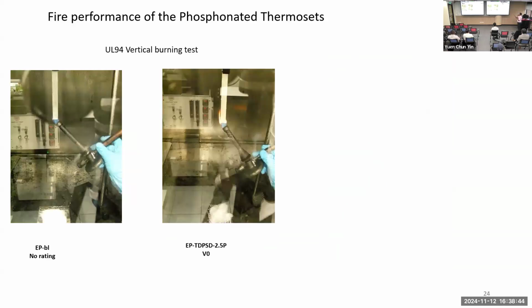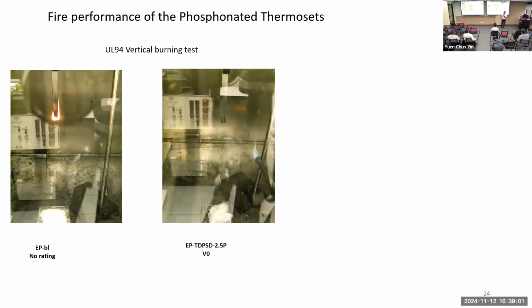Of course, I showed you how the recyclability works, but does it work as a flame retardant? Because that's also our goal. You can see to get recyclability, you don't need as much phosphorus, and to get fire protection, you need more amount of phosphorus. Okay, that is something which you have to keep an eye on. On the left, it is an epoxy resin, which is actually burning, dripping. On the right is the dynamic network, which has 2.5% phosphorus, and it doesn't burn, I would say.